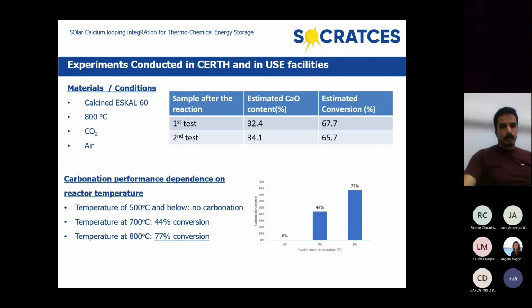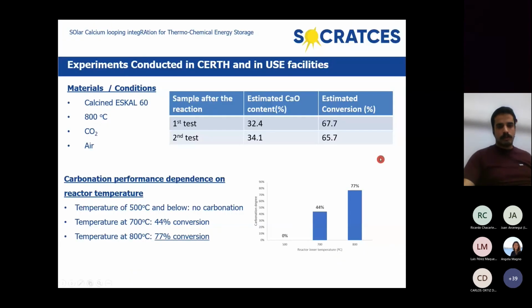Finally, we can see some of the results. First, the conversion was tested here in our facilities in CERTH with some preliminary experiments. And we achieved carbonation around 65% at a temperature of 800 degrees Celsius. And next, it was tested in the prototype unit in Seville.